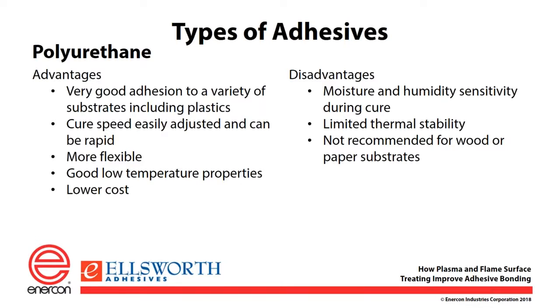Another issue with polyurethanes is they have limited thermal stability. If you have a service temperature requirement above about 125 degrees Celsius, a polyurethane is probably not a good choice. But if you're at 125 or below, you're in good shape. They're not recommended for substrates like wood or paper because they have moisture present.